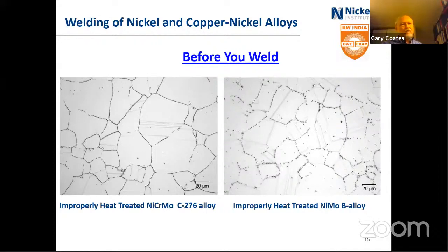But if you don't require an acceptance test for the material, you order it from the cheapest source, you may end up with badly heat treated material. And then if you go to weld it, you will do a very bad job on welding. Physically, it will look good. It will actually corrode very rapidly in service.